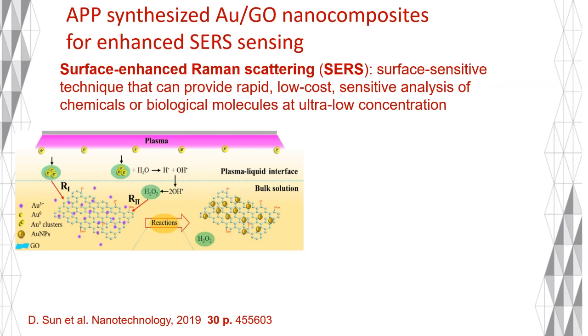In this follow-on study, we focused on exploring the application of graphene oxide, another functional material from the nanocarbon family, in combination with gold nanoparticles again, to create a gold graphene oxide nanocomposite. Our goal here was to demonstrate their efficacy for biosensing applications, specifically surface enhanced Raman spectroscopy, or SERS sensing. We may know that graphene oxide possesses unique structural and excellent mechanical properties. It is also rich in surface functional groups, and these functional groups facilitate its dispersion in water and enhance biocompatibility. When graphene oxide is combined with gold nanoparticles, the resulting composite can harness the localized surface plasmon resonance properties of gold, along with the enhanced electron transfer within the graphene oxide structure. And this combination makes SERS sensing possible.